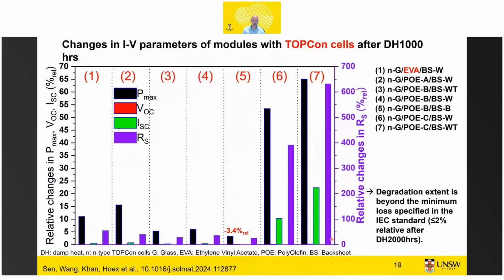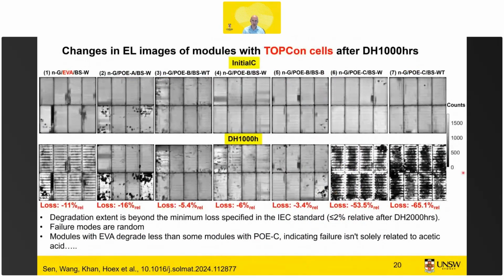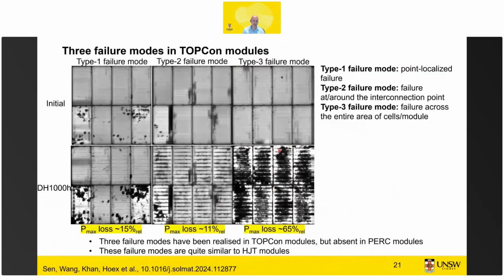And this degradation was mainly related to an increase in series resistance. So this was related to the metallization being compromised. So if we look at the EL images, we see that the worst performing, that was POE-C, was showing this type 3 failure that I showed earlier. And that's then the failure mode we looked into in a lot more detail. It was yes, the most severe one. There's the second one that was actually acetic acid. So you can solve that by not using EVA or EPE, it's a lot less. And this again was just contamination, but this is easy to fix. This is also easy to fix. This one, we have to understand the root cause.